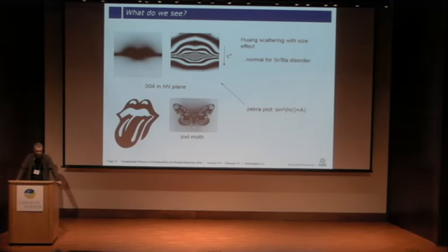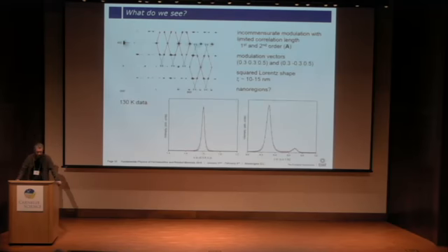Well, then, Huang scattering with size effect. However you represent it, you can call it a butterfly, or you can call it differently. It's here, it's weakly dependent on temperature. And it's superposed with thermal diffuse scattering, and it's superposed in the same place with Lorentzian-shaped diffuse scattering. So it's really a big pain.